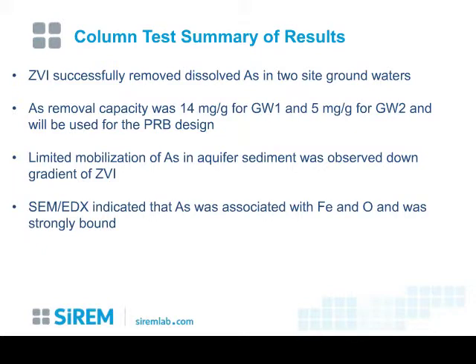So again, we were able to successfully determine that ZVI removed dissolved arsenic in the 2 site groundwaters. We were able to determine specific removal capacities that were used for the design. We were able to demonstrate that there was limited mobilization in the sediment down gradient of that. And the scanning electron microscopy indicated where it was bound and that it was strongly bound.